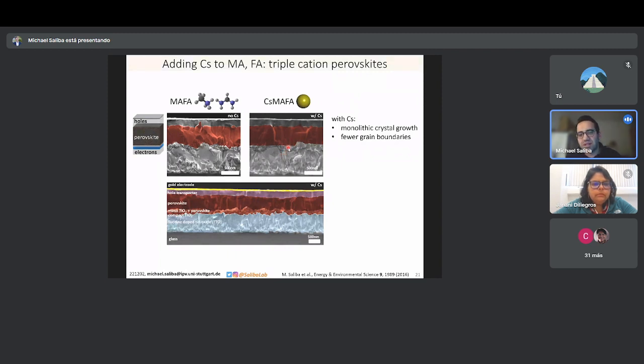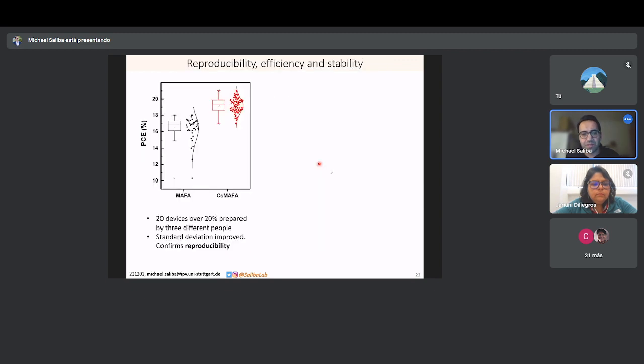So quite different situation. And the sensitivity hypothesis was also proven here. We had a lot of variability when analyzing the MAFA perovskites. Even here we had devices that went as low as 10%, but people usually don't report on them. So this is the problem sometimes. And then only 18% was the maximum we could reach. But then upon adding the cesium, all of a sudden our baseline started off at 17% with top values towards 21%.